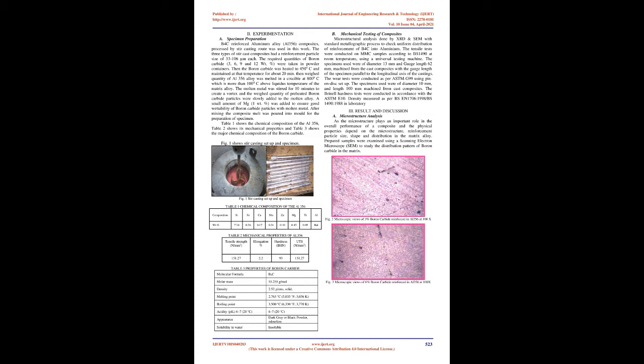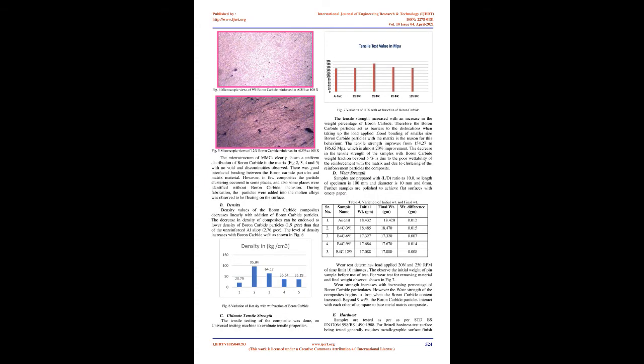2. Experimentation. A. Specimen preparation. B4C reinforced aluminum alloy, Al356, composites processed by the stir casting route were used in this work. The stir cast composites had a reinforcement particle size of 53 to 106 µm each. The required quantities of boron carbide, 3, 6, 9, and 12 wt%, were taken in powder containers.